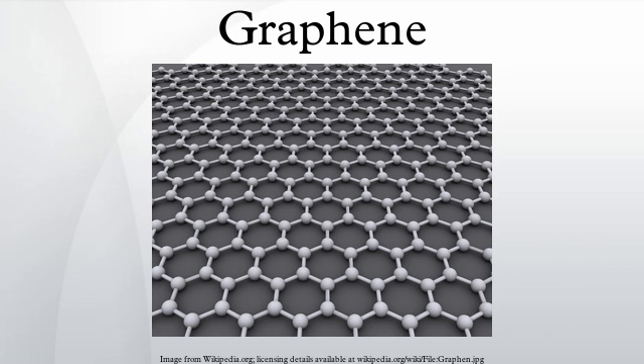Exfoliation. As of 2014, exfoliation produced graphene with the lowest number of defects and highest electron mobility. Adhesive tape. Cleavage is also known as exfoliation. Achieving single layers typically requires multiple exfoliation steps, each producing a slice with fewer layers, until only one remains. Geim and Novoselov used adhesive tape to split their graphene. After exfoliation, the flakes are deposited on a silicon wafer using dry deposition. Crystallites larger than 1 mm and visible to the naked eye can be obtained with a technique often referred to as the Scotch tape, or drawing method. The latter name appeared because the dry deposition resembles drawing with a piece of graphite.